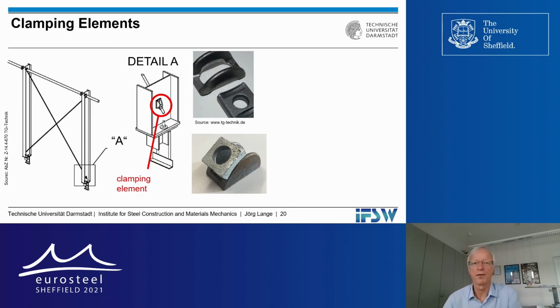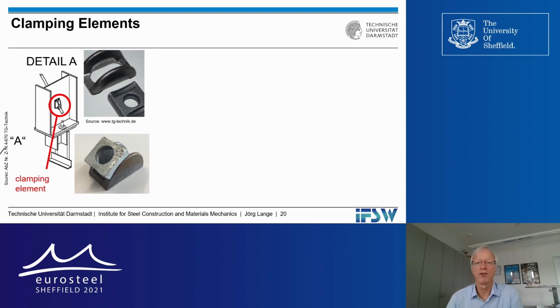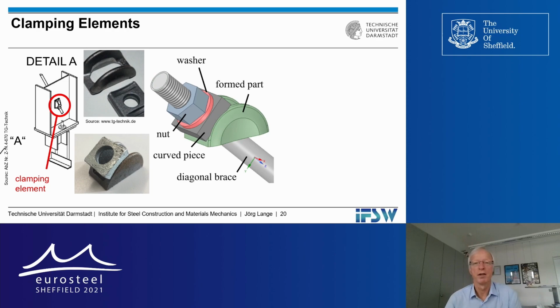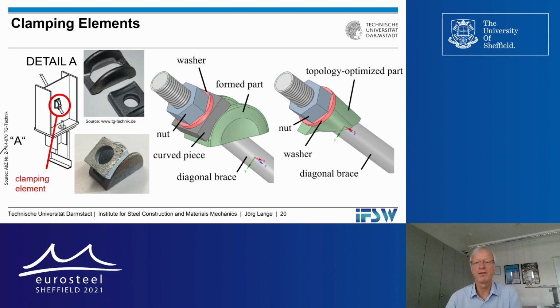Another point that I wanted to show to you are these clamping elements that are used to fix wind bracings around steel. And in the web, you use these cast iron plates, as you see in the center top, two elements, and in the center bottom, you see how they are put into place. So this half moon shape is welded to the flange. And then you have this special plate where you can fix a nut and a washer and introduce your wind bracing forces. You can also print this, again, topology optimized, in exactly the angle you need. And you don't need these two cast iron elements that have to be put into place. They have to be welded. And again, you save all the logistics. And you see here the final result as we printed it.